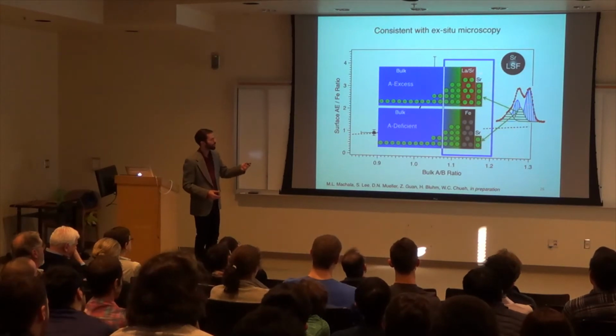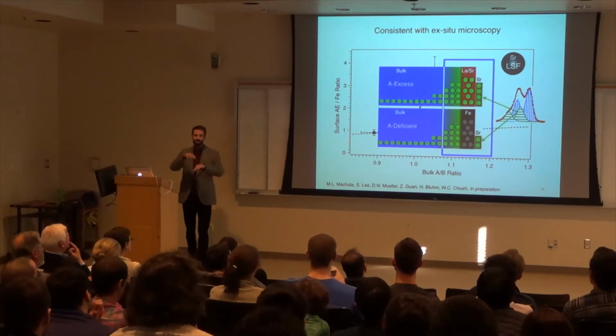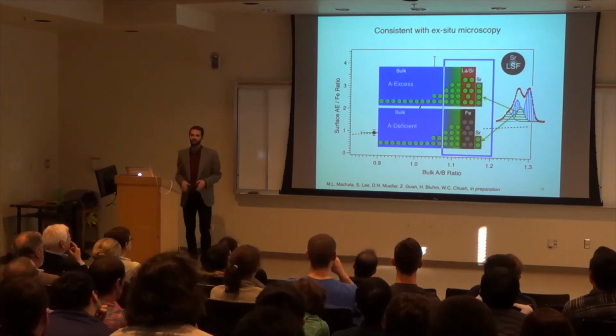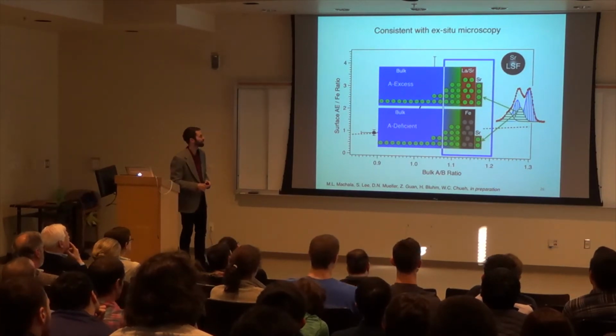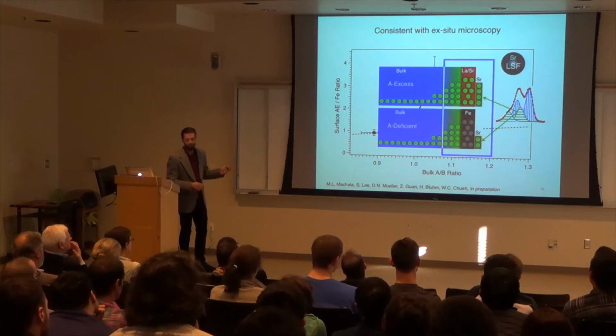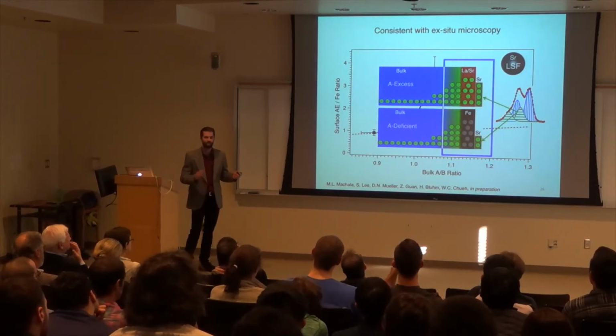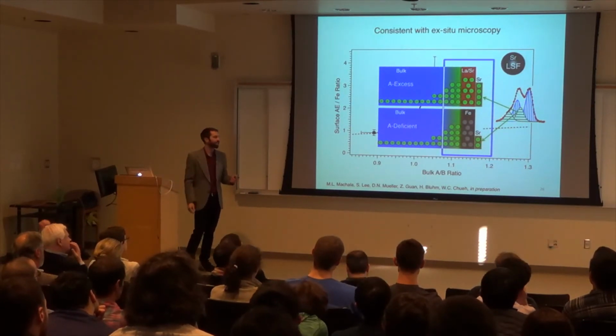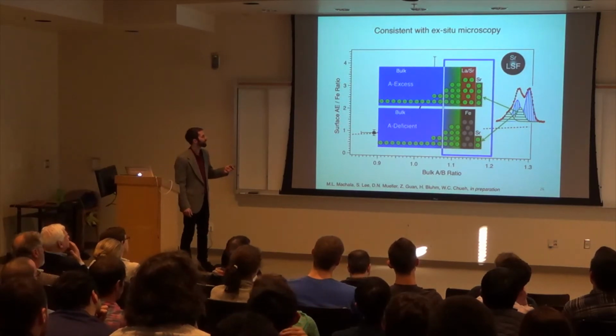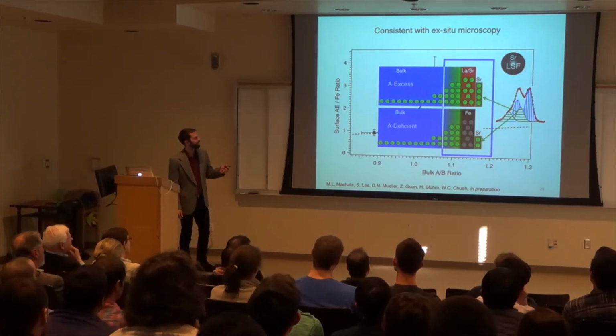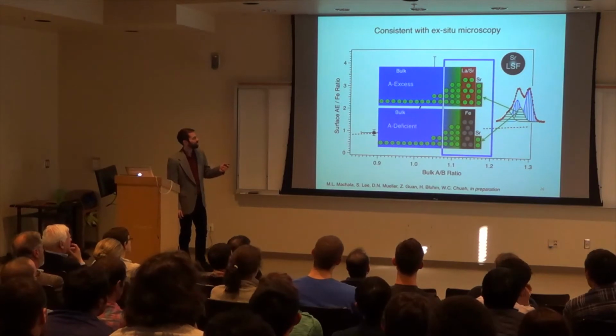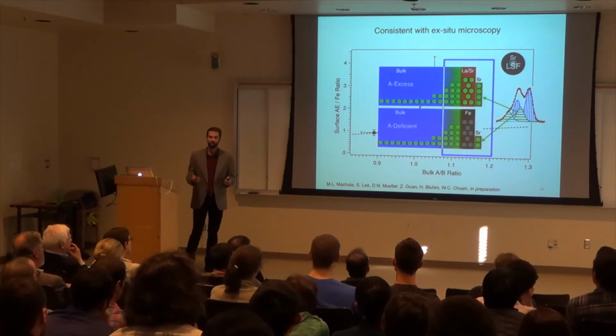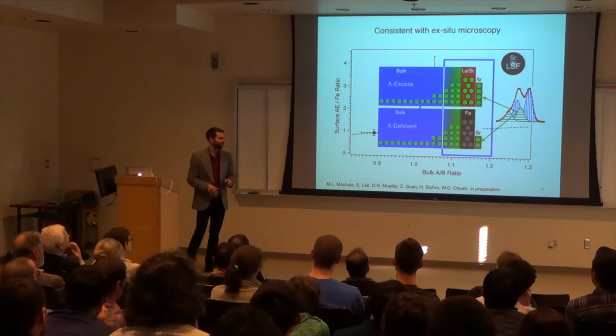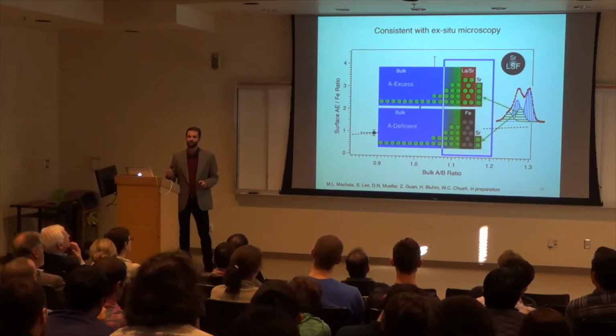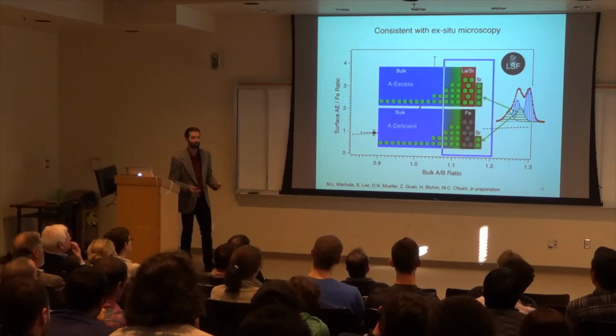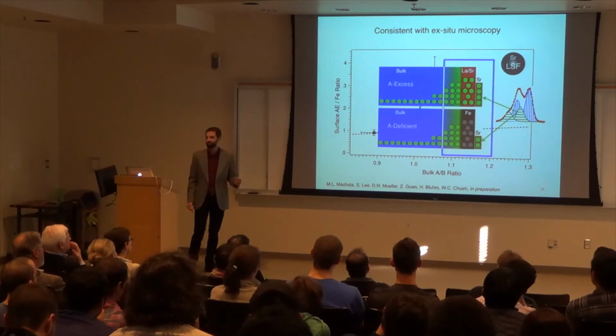Essentially that side peak signature is these atoms, kind of just like a monolayer or so, found at the top of the surface. And so we can also extend this, not just to the strontium sample, but now we can look at the barium samples as well. And what this also tells us is that electron microscopy is not the best way to see if something is precipitating or not. Those images that I showed you at the surface are not the best way to tell. You actually see atoms on the surface, and you can't resolve them with the electron.